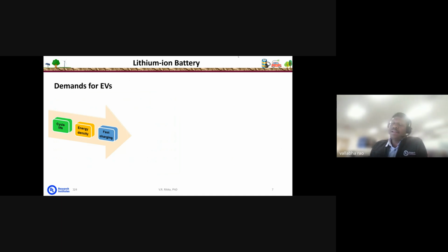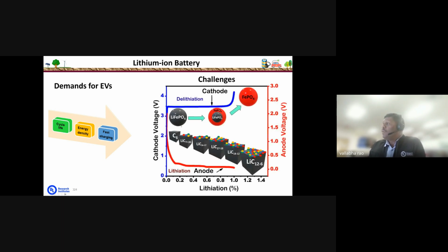But coming to electric vehicles, which demand more precision, the cycle life of the lithium-ion cell should be high while we utilize the high energy density from the individual cell at fast charging. This is a very critical condition. For example, we can consider a simple chemistry, LiFePO4, lithium iron phosphate, with graphite as the anode. When we are charging, the lithium ions are removed from the lithium iron phosphate and inserted into the graphite electrode. This process occurs simultaneously: removing the lithium ions from the cathode while inserting them into the anode side.